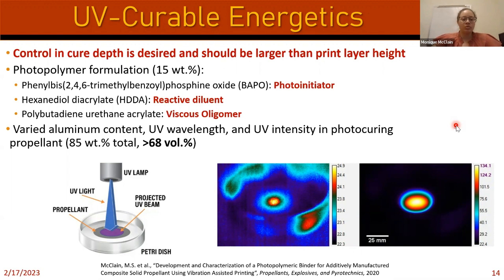So what we did was we looked at trying to make a new commercial off-the-shelf mixture. We tested the photopolymer mixture first, and then we added 15% of that to a mixture with ammonium perchlorate and aluminum. So we had 85% of those, but focusing on the photopolymer first, we picked BAPO as our photoinitiator because that's a fairly common photoinitiator with a higher wavelength, and it was definitely not that toxic compared to other ones that are out there.